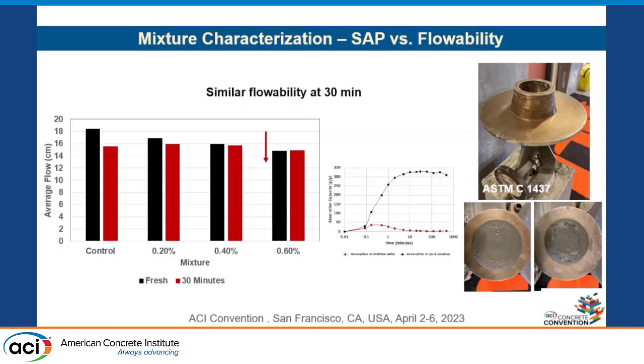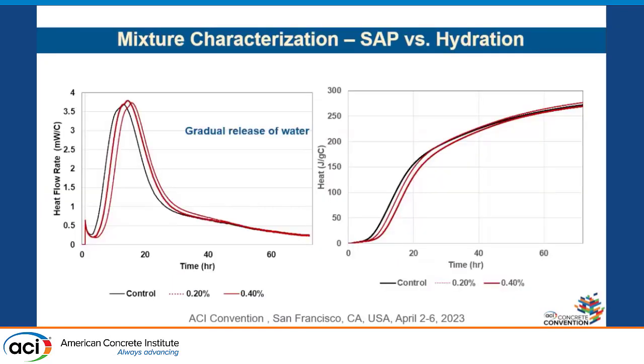And the other thing, we wanted to figure out what's going on exactly. So we did hydration scanning, and you see the results here. Of course, I have only the results for control, 0.2% and 0.4%. And as you see, as we are increasing the amount of SAP, the hydration is decelerating, and it's mostly because there is less available water in the mixture for cement hydration. So that's one of the reasons that the flow of the mixture decreased.